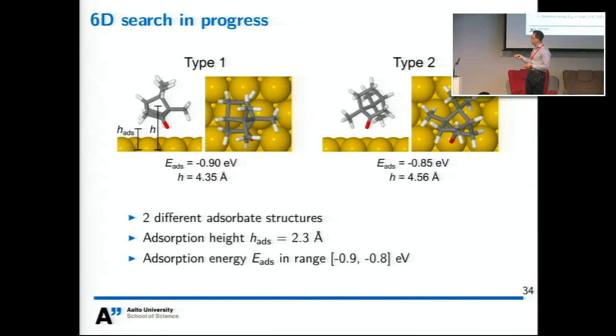In both of these, the adsorption height, determined as the separation between the lowest part of the molecule and the surface, is similar, 2.3 angstroms. And the adsorption energies of both of these are also fairly similar, roughly minus 0.9 electron volts.